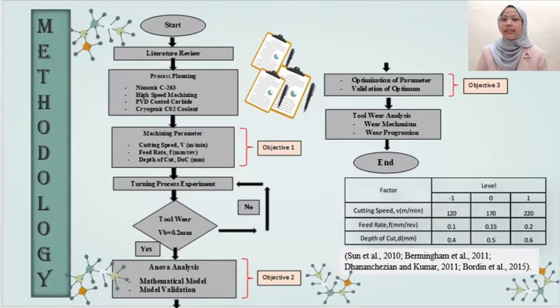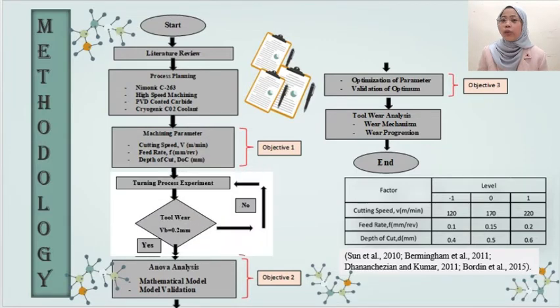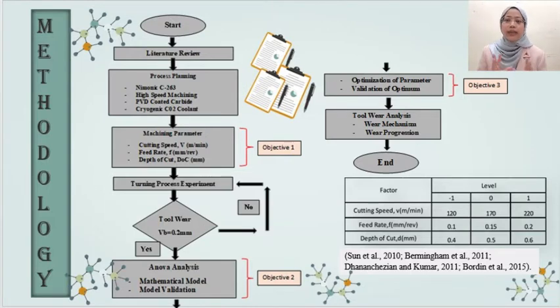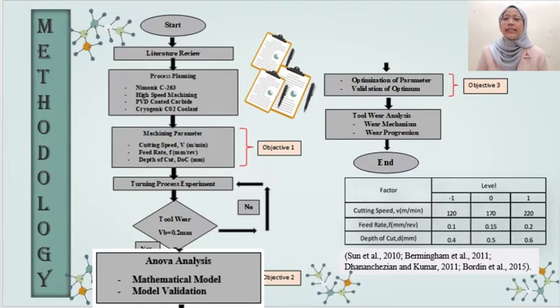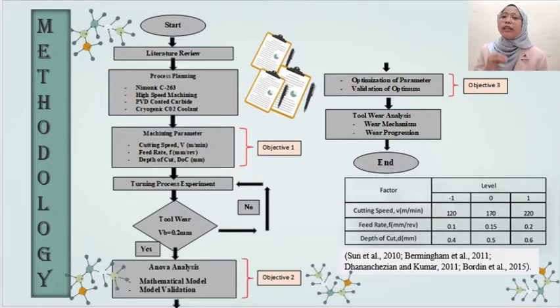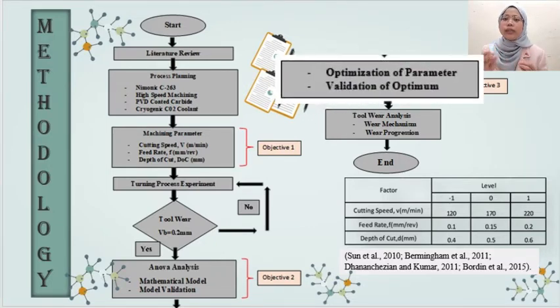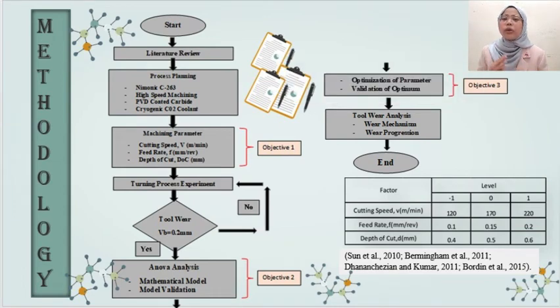In this turning process experiment, the experiment continues using the same cutting tool until the tool wear VB reaches 0.2 mm. If the tool wear has not achieved 0.2 mm, continue machining. If yes, then do the ANOVA analysis. In this ANOVA analysis, the mathematical model is developed to indicate the relationship among parameters on the tool life. By conducting the experiment, we can know the accuracy between the developed mathematical equation and the experimental result. Here for objective 2, the optimization is conducted with the aim of the highest tool life value until the pre-optimal parameters are selected. The accuracy of the pre-optimal parameters is also verified by the validation experiment.